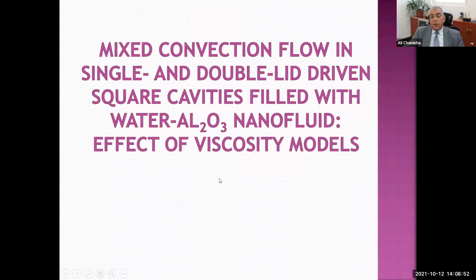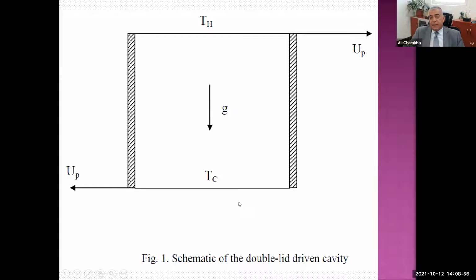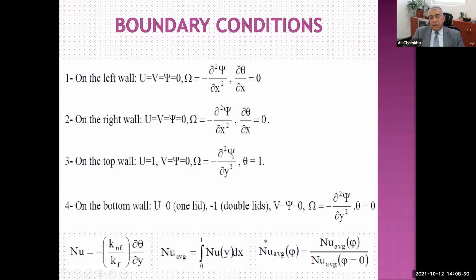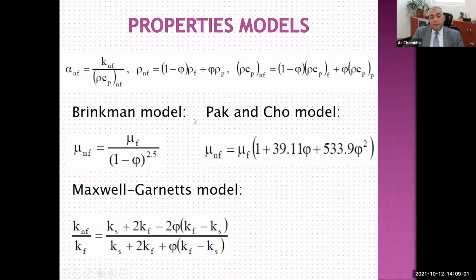Now, if you go to another problem, which is the double lid cavity, similar calculations. The important thing here is the use of different viscosity models for nanofluid. This is the original Brinkman model. This is the Pak and Cho model that was used based on experimental data. This is still the Maxwell-Garnett model. So we used a different problem. We compared the Brinkman model and the Pak and Cho model.